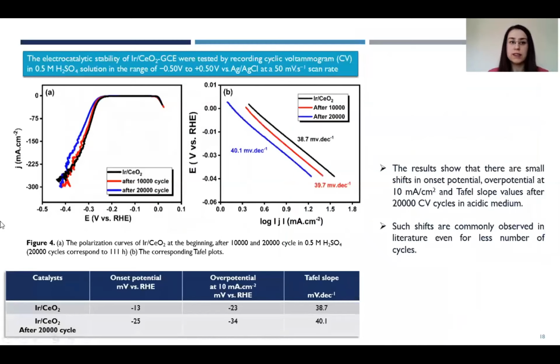The electrocatalytic stability of the iridium ceria was tested by recording the cyclic voltammogram in 0.5 molar sulfuric acid solution at a 50 millivolt per second scan rate. The results show that there are small shifts in onset potential and overpotential at 10 milliampere per centimeter square. Also the Tafel slopes after the 20,000 cyclic voltammetry cycles in acidic medium.